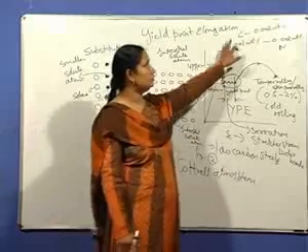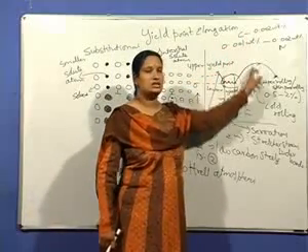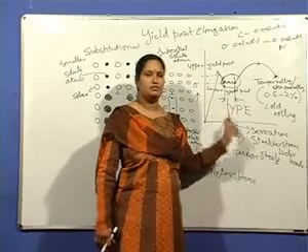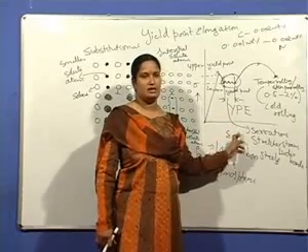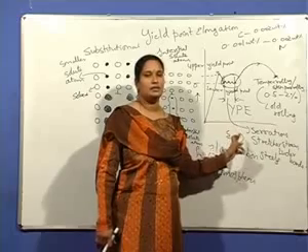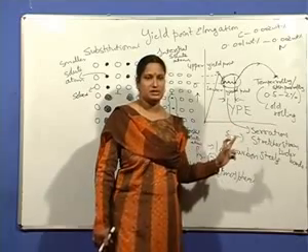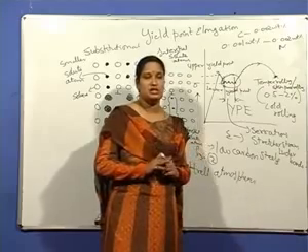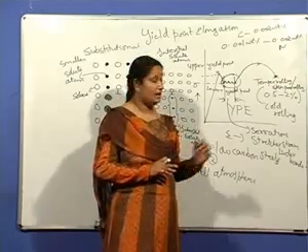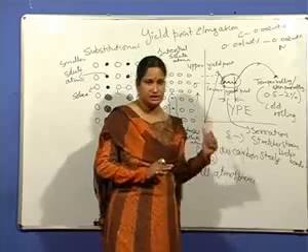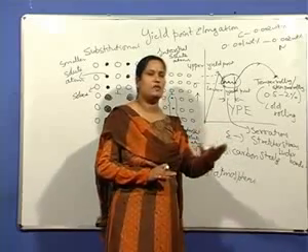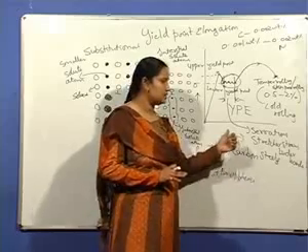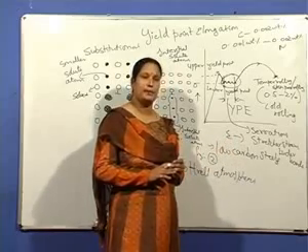A minimum amount of carbon and nitrogen is required to cause this effect. This forms an objectionable surface on low carbon steel sheet materials, mainly in sheet forming. It gives a very rough appearance on the surface due to these stretcher strains, also known as Luder bands.